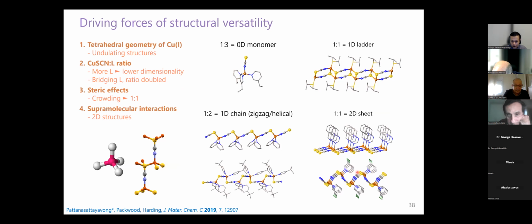Like if we choose chloropyridine, 3-chloropyridine, in this case it is also 2D because this one here expands in 2 dimensions. Okay, and there's no bonds between this layer and the next layer because they are capped by the pyridine derivatives here. It's not like a flat 2-dimensional sheet, but it's a 2-dimensional layer structure. And also if we add more, they would form 1-dimensional chains like this.